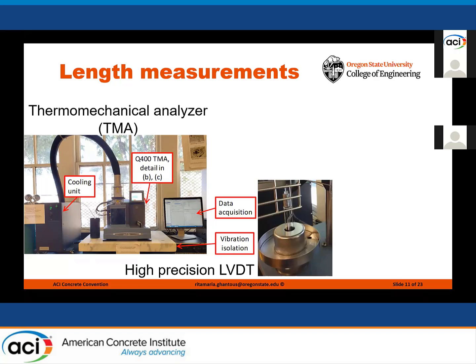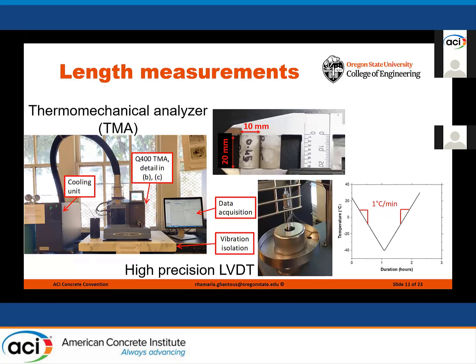Length measurements are performed with an accurate LVDT, and you can see that the temperature is decreased from 24 degrees C to minus 40 degrees C at a cooling rate of 1 degree C per minute, and is heated up to 24 degrees C at a heating rate of 1 C per minute, which makes the length of the test only 2 hours. In this procedure, we test a smaller sample with 10 millimeter diameter and 20 millimeter height. These can be conditioned fast to the value we want, so with this technique we can test lots of samples in quick timing.